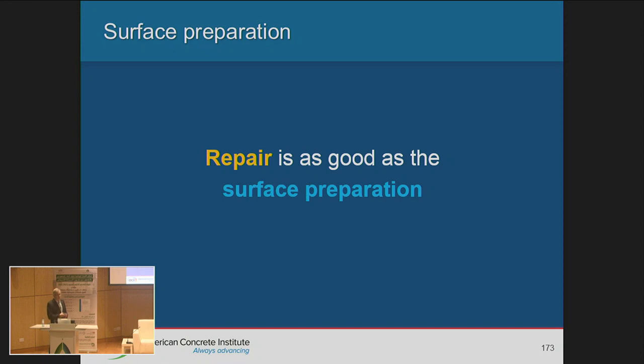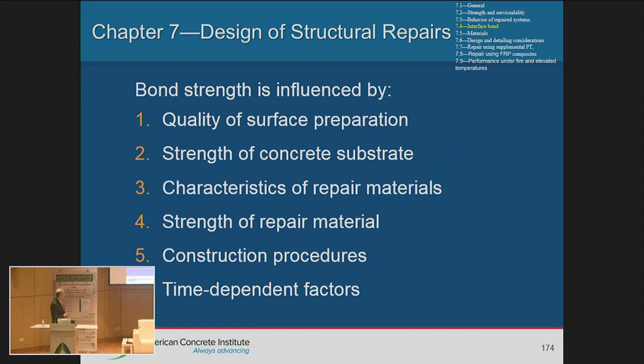And as I mentioned, when we look at the repair, when you're adding an overlay or new material to an existing material, the repair is as good as your surface preparation. So if the surface is not well prepared, you're not going to get a good repair. Your repair is going to fail. And if you remember when we talked earlier this morning, we talked about the failure rate of repair. It was about 70% within 10 years.